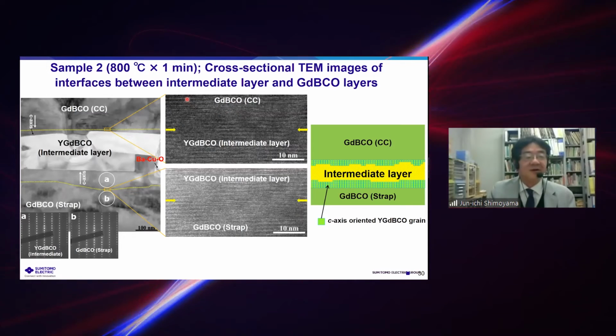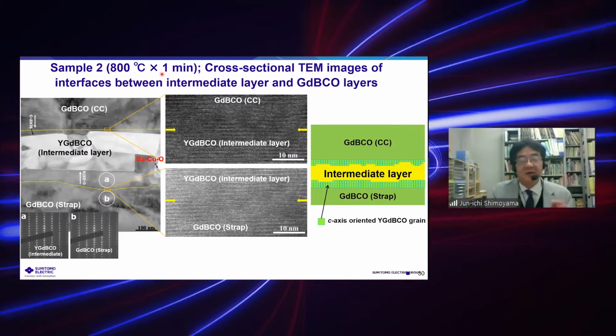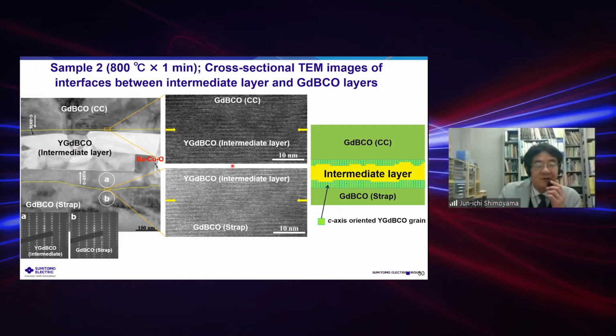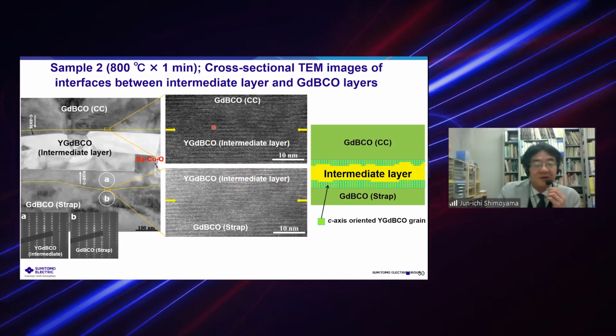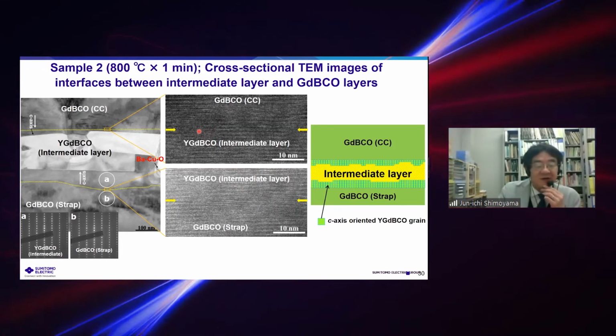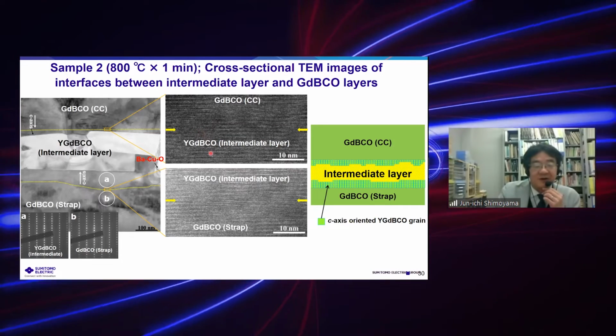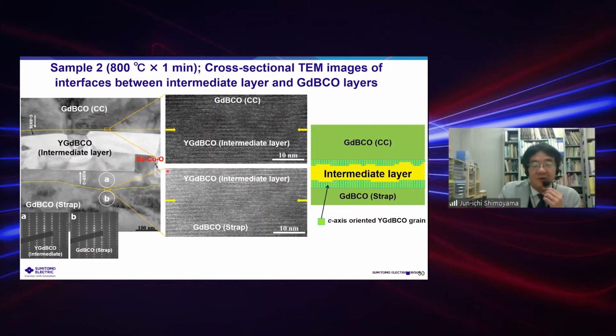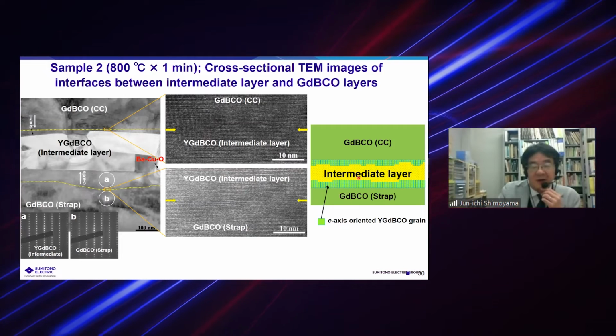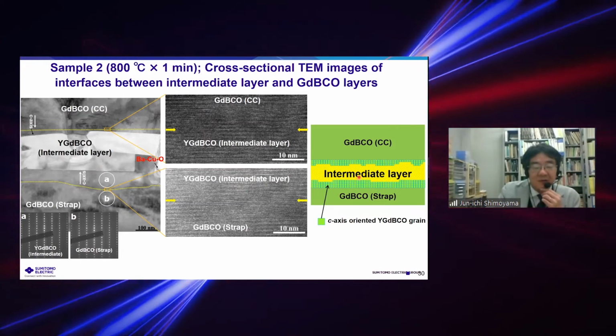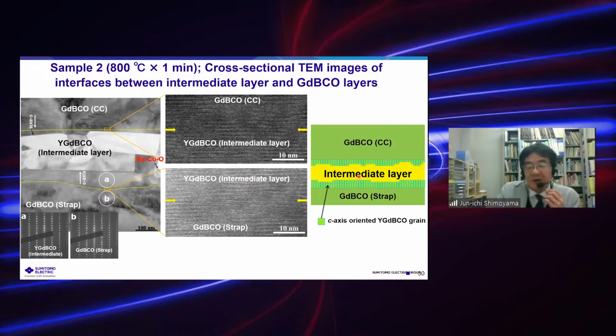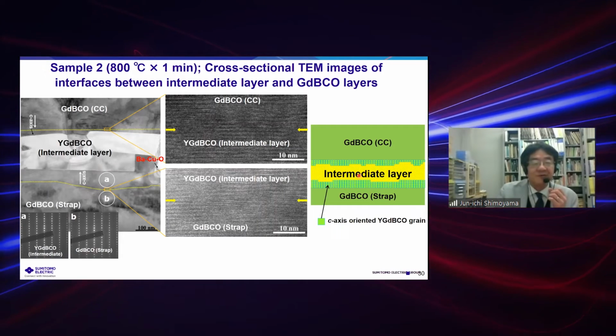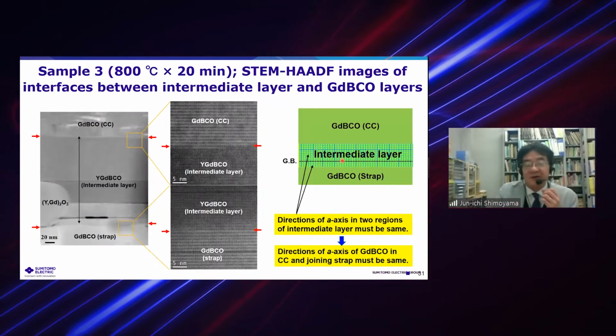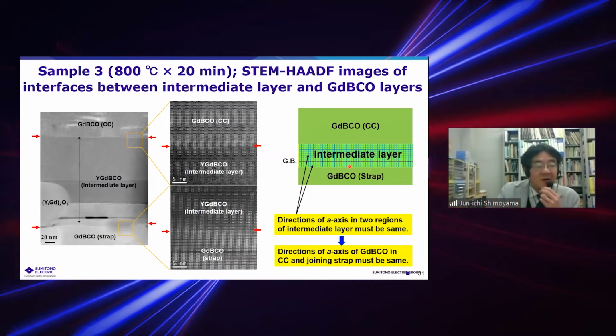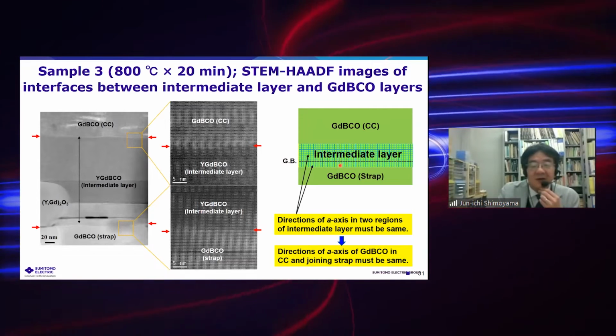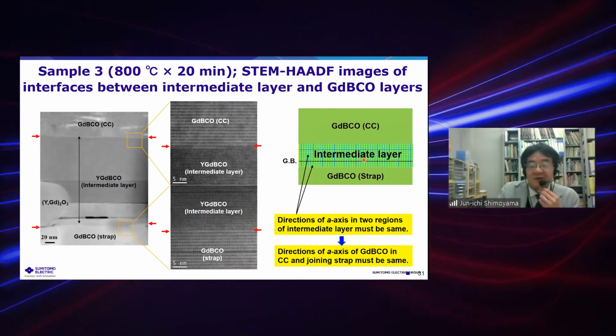After sintering at 800 degrees C for 1 minute in reducing atmosphere, the c-axis-oriented intermediate layer started to grow from the interface, as you see here. The middle part of the intermediate layer remained randomly oriented small grains. After 20 minutes, all the intermediate layer turns to very well crystallized gadolinium yttrium-123 layers, as you see here.